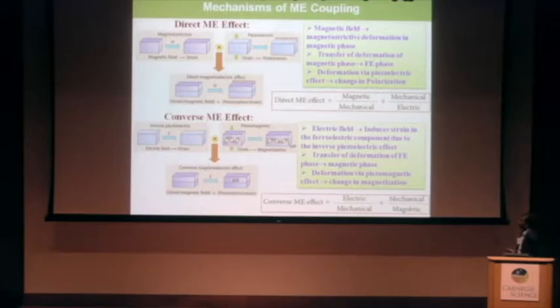Magnetoelectric coupling is normally indirect coupling, and it is via strain. Here, there are two types of coupling. One is direct magnetoelectric coupling, and another is converse magnetoelectric coupling. The direct means by applying a magnetic field, we can change the electrical order parameters. Here, when we apply a magnetic field, magnetostrictive deformation occurs in the magnetic phase, and it transfers to the ferroelectric phase. Then, due to the piezoelectric effect, we can see changes in the order parameter. And in the converse magnetoelectric effect, by the application of an electric field, we can see changes in the magnetic order parameters.